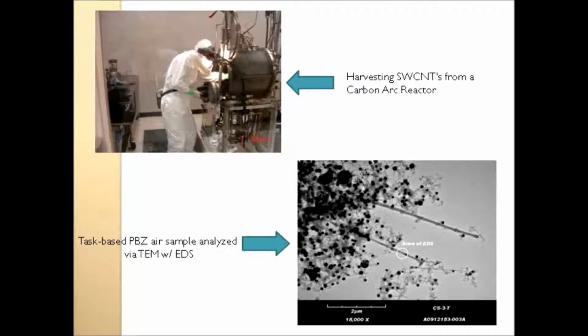Okay. An example here is an actual worker making carbon nanotubes. They're single-walled carbon nanotubes in an arc reactor. You can see he's got a lot of protective gear on. He's reaching into a reactor, and he's collecting and harvesting that material. Again, this is a filter-based sample looked at under transmission electron microscopy with EDS so that we can identify which material is which. You can see there are some fibrous structures here, but for the most part it's a large agglomerate of sooty material containing residual catalyst. So this is raw material coming out of the reactor, and it's showing you that it can, if he was not protected, migrate to the breathing zone.